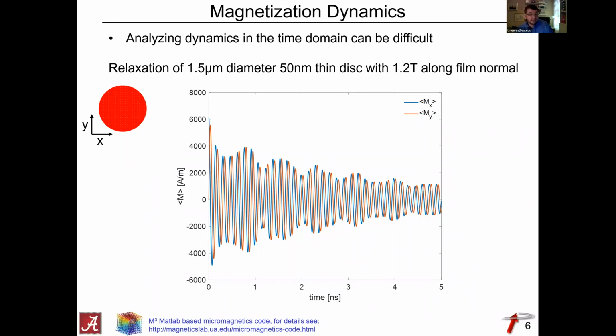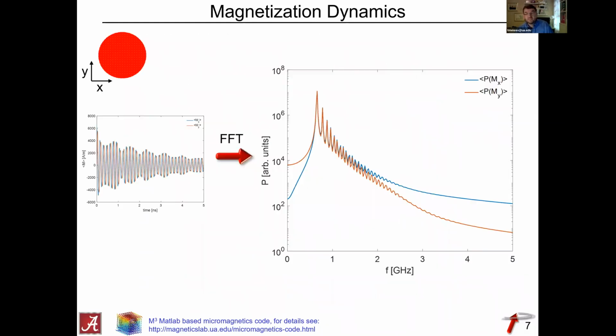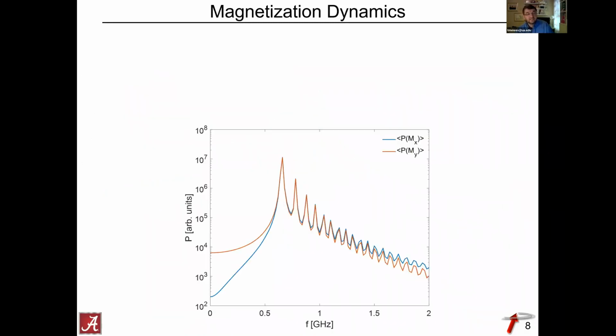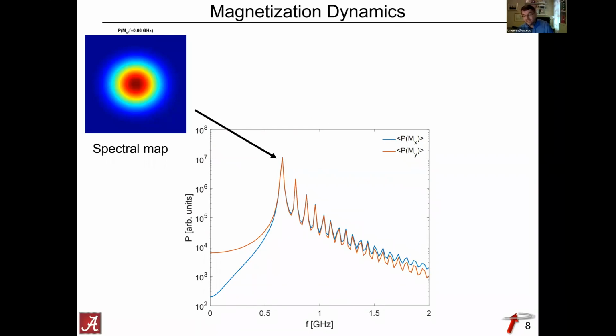And if you look at this information in the time domain, it's difficult to figure out what's going on here. So why do we see these different oscillations? You might have some ideas, but typically what we do in physics is take the Fourier transform of the data, and things get a whole lot clearer once you do that. What you see are these pronounced peaks in the Fourier spectrum. And so now you can start identifying those peaks. For example, this first peak here in the power spectral density is just the fundamental mode of your disk.